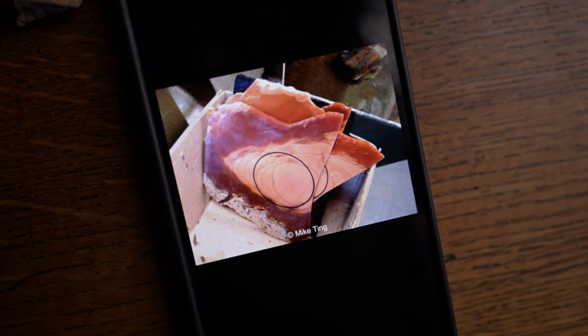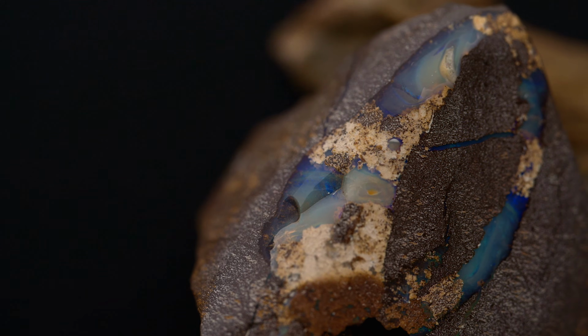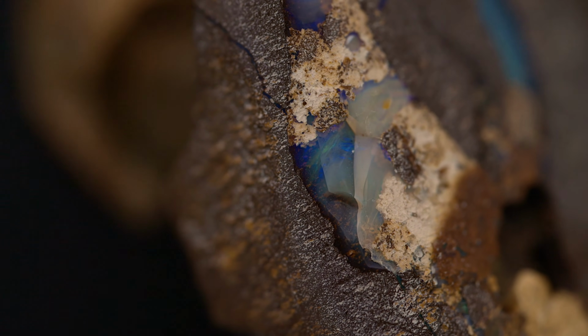In the 1960s, when the process was still experimental, many dials broke during cutting or when the hands were set. Therefore, stone dial blanks were cut to an initial thickness of 1 mm as opposed to the 0.4 to 0.6 mm required for conventional dials. First of all, getting the right stone takes time, because you need to be absolutely sure of the quality and purity of the material as well as the reliability of the supplier. Then it takes a skilled craftsman to cut and polish the stone to perfection, without affecting the natural color gradient or texture, while keeping the color and layers intact.